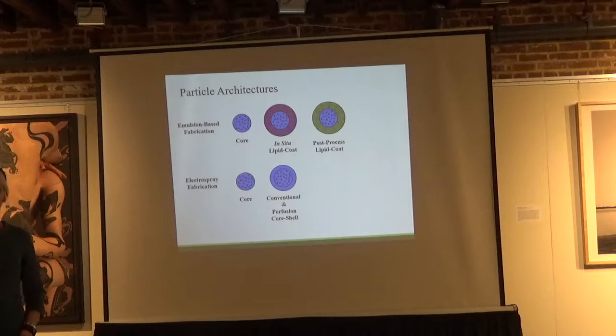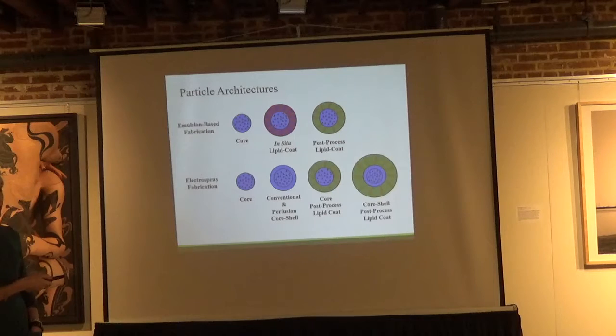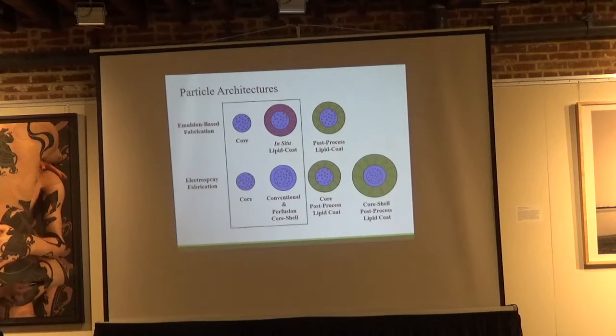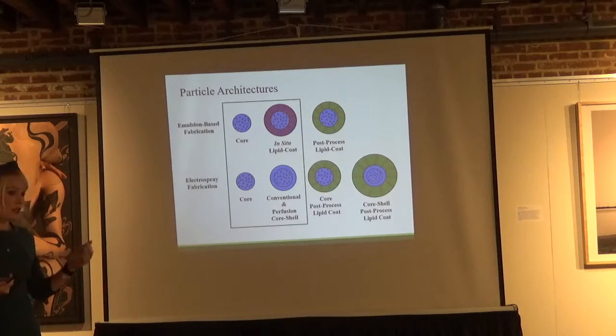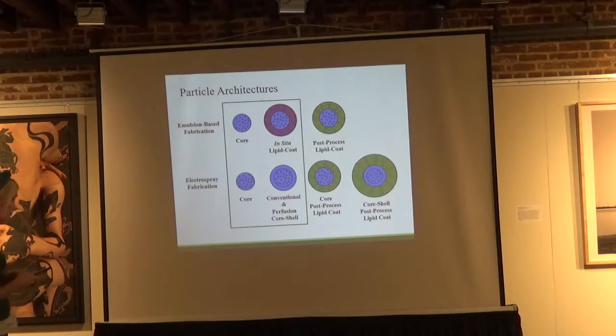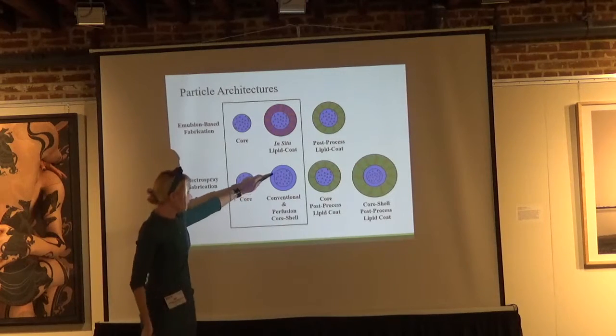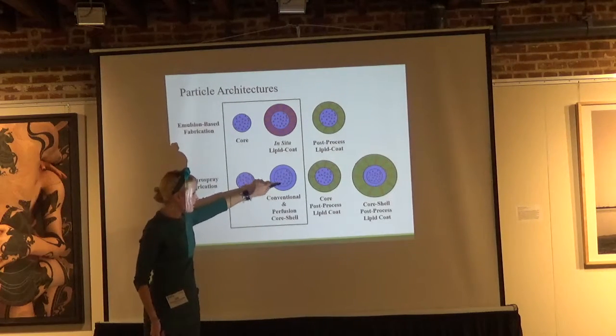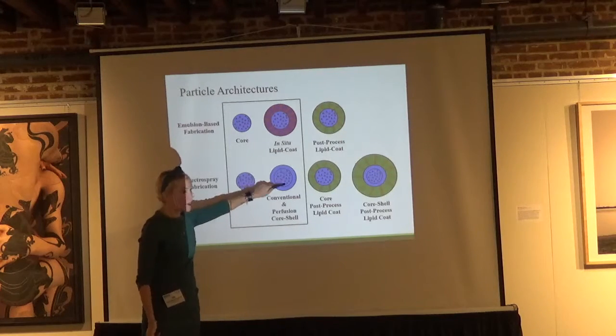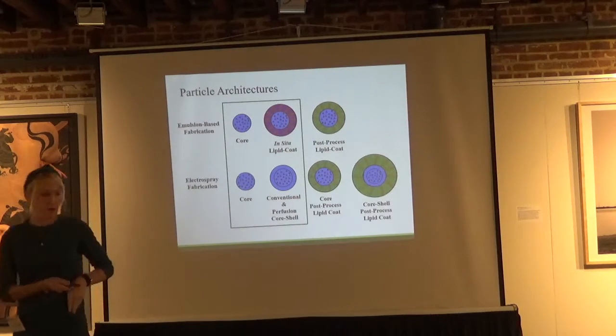And here, looking again, you can spray core particles, you can spray a conventional core-shell particle. And you can look at what happens if you put lipid coats on these to make hybrid lipid-polymer particles. And so I'm just going to show you some preliminary release work from this summer in the lab, comparing our core and our in situ lipid coated with the core electrosprayed in two different types of electrosprayed particles, what I call conventional and perfusion. And the difference is that in the conventional, we had the PLGA matrix on the shell, PLGA matrix with drug in the middle, whereas the perfusion only had drug in the middle and no polymer.